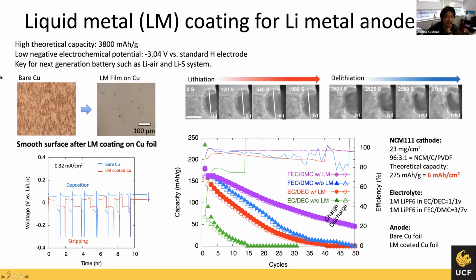The idea here is to use a liquid metal as a coating material on the anode to prevent the lithium dendrite. This is a liquid at room temperature. It is a gallium-based alloy, and the melting temperature is about minus 10 degrees Celsius, so you can maintain the liquid state at operating temperature.